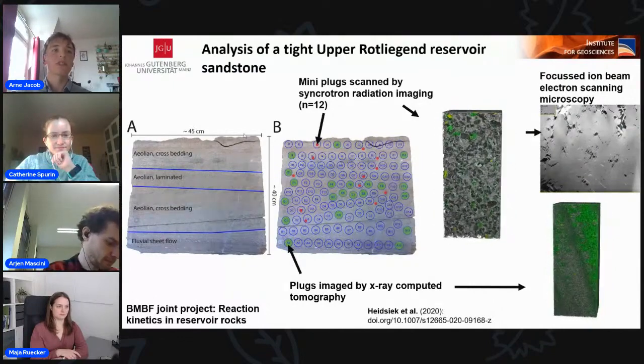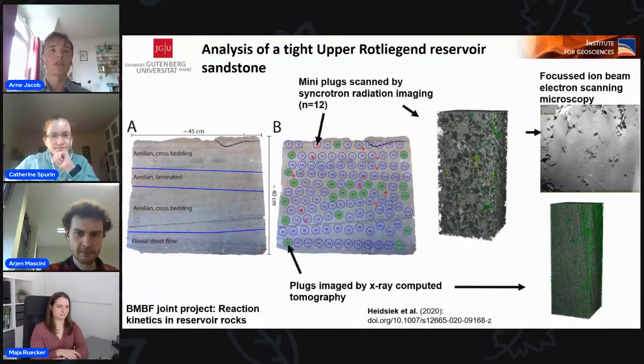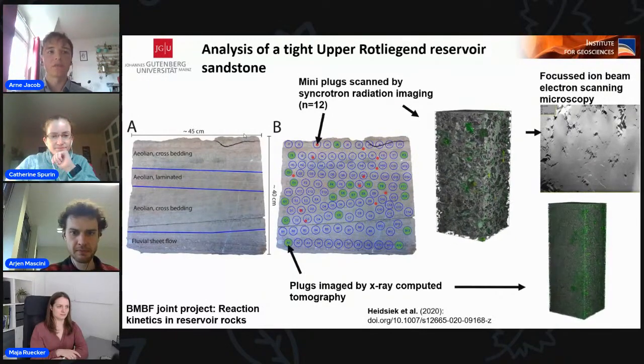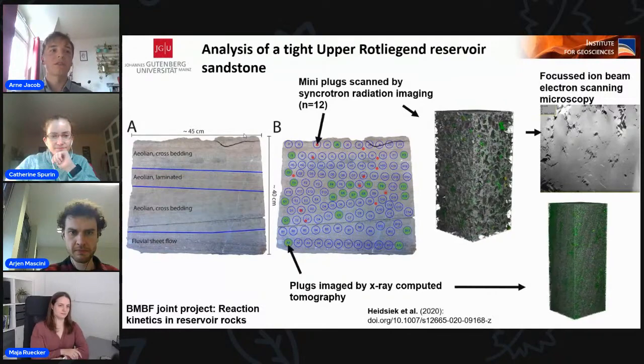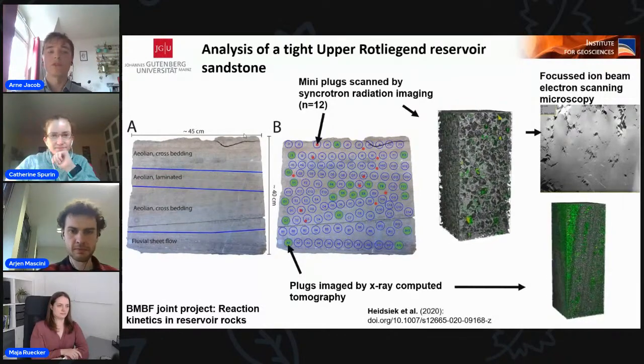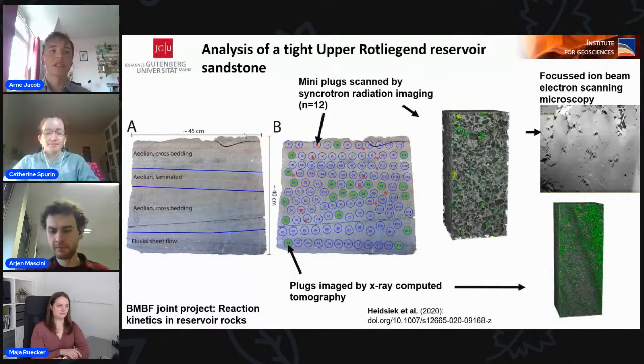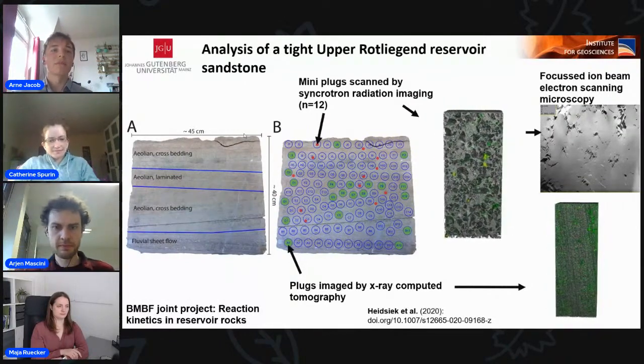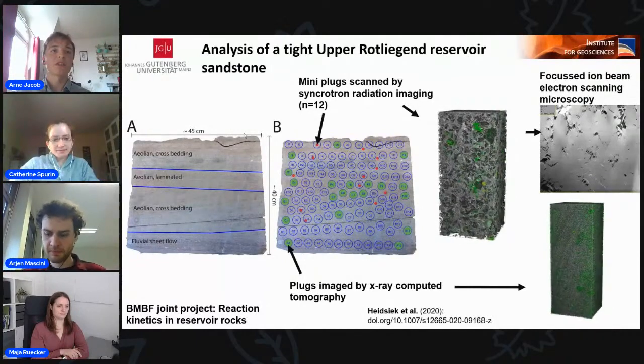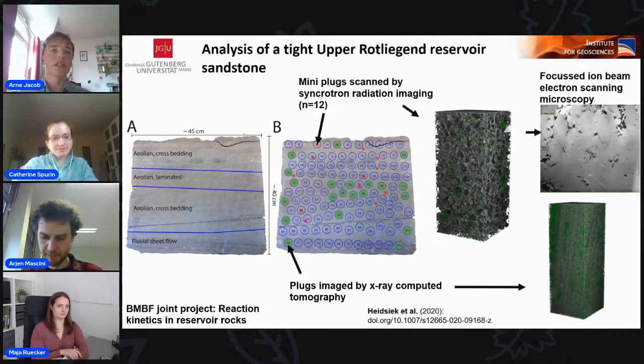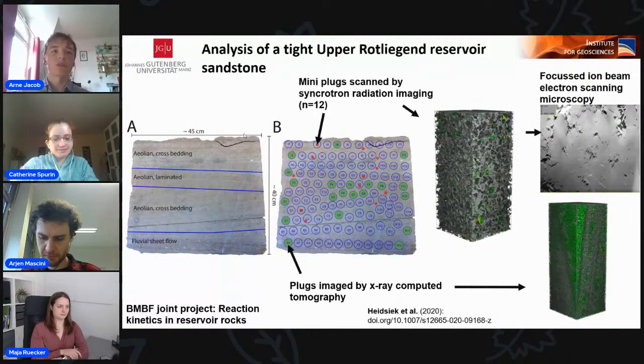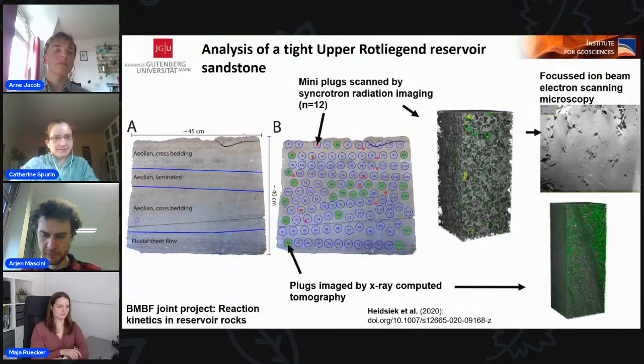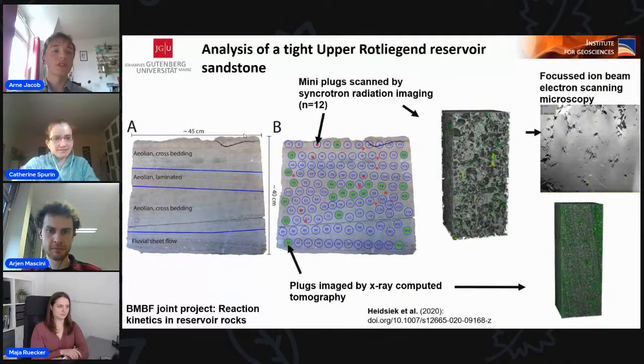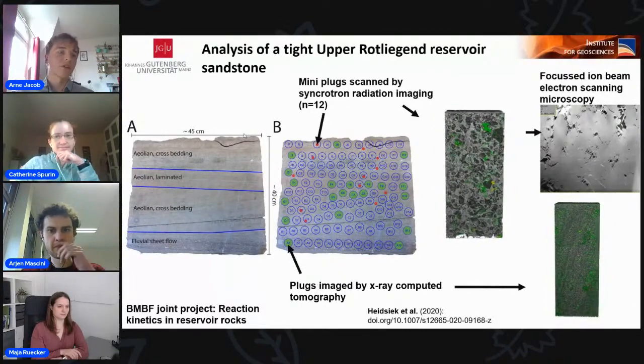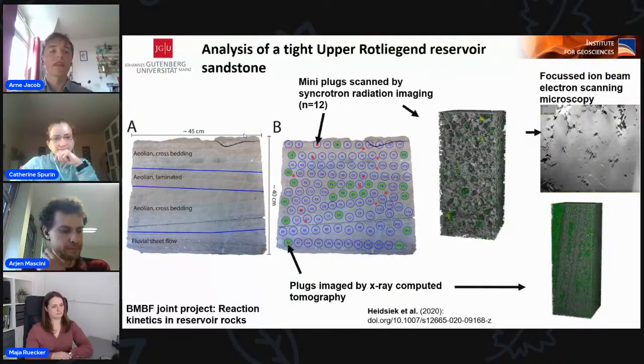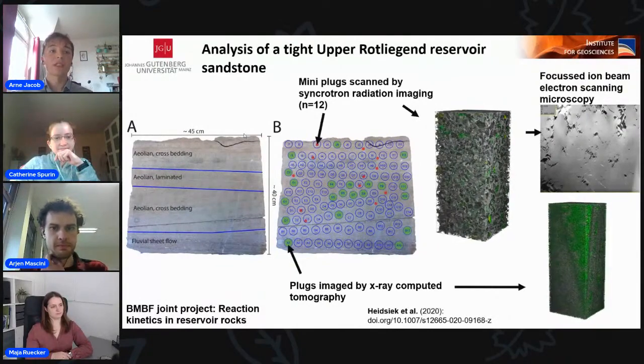During the post-processing, several steps must be taken to obtain a high image quality. This is especially filtering and segmentation. Since there's always noise in the images after reconstruction, one has to filter them by applying image filters, for example, non-local means filters, Gaussian filters, or median filters. The segmentation can be done by using conventional grayscale thresholding, where you just set a threshold in your gray value intensity level of each voxel, which separates the pores from the grains from the calcite, and so on. By doing so, one can determine the porosity and other important parameters like surface area, curvature, pore size distribution, and so on. We did this for each size of the different plugs we had.